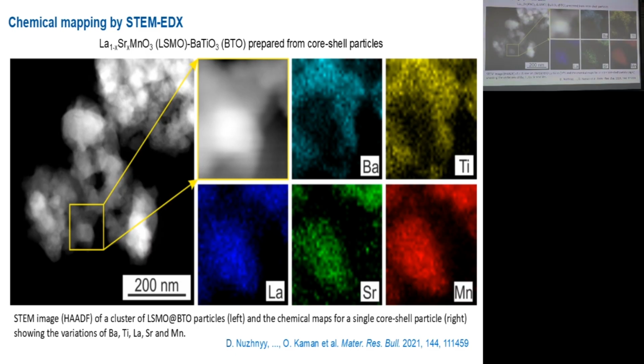In this case, it was a composite formed from this perovskite and barium titanate, another perovskite, and we can see some lanthanum strontium manganite cores coated with barium titanate. And this kind of imaging was very important because both the phases have similar contrast in the bright field imaging, and you cannot clearly distinguish them. So just by chemical mapping, you can see that we have this core shell structure.